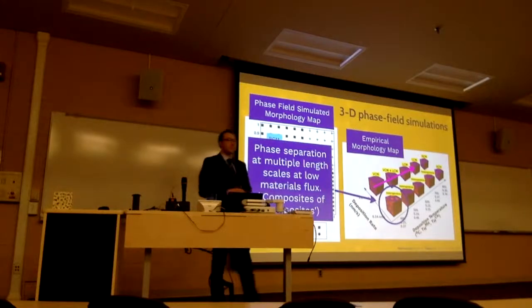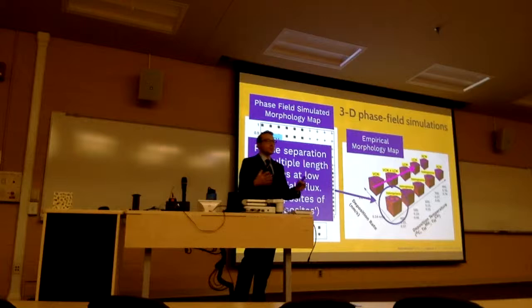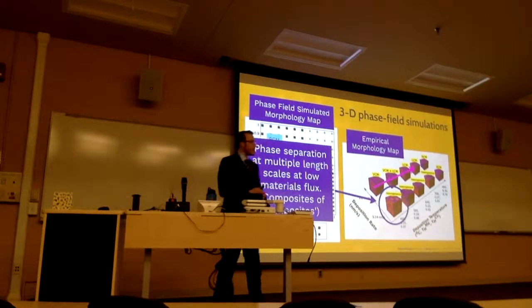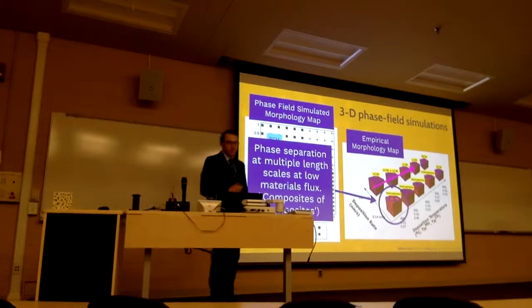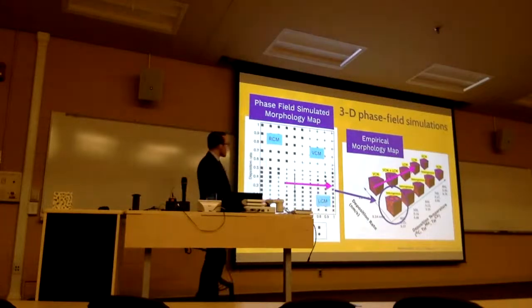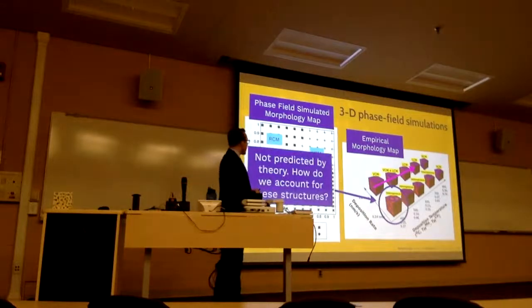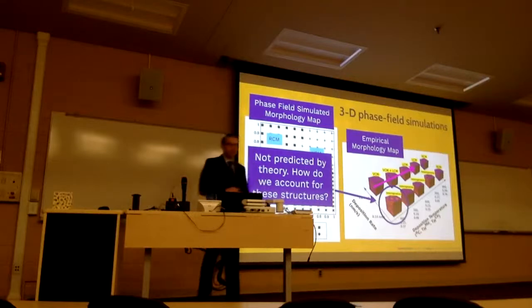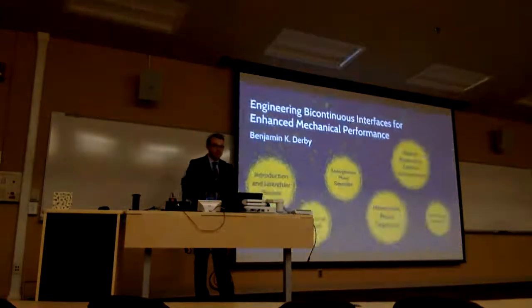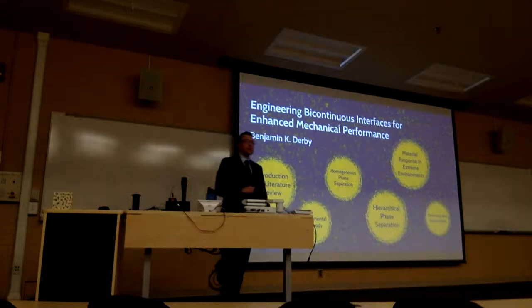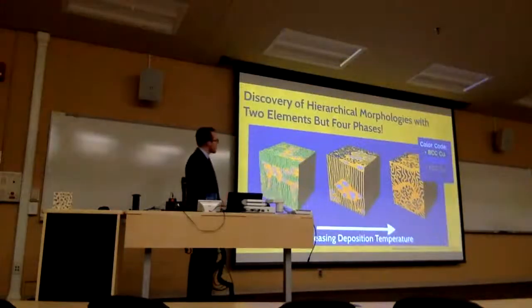It's actually a phase-separated structure that has multiple lengths or multiple scales of phase separation during deposition. We dub these composites of composites. But if you look at our model, it doesn't actually predict a hierarchical-like morphology based on the deposition conditions. So we ask the question, how do we account for these structures? And that's where I'd like to go next, describing this hierarchical phase separation during deposition. Here's a summary of those results.